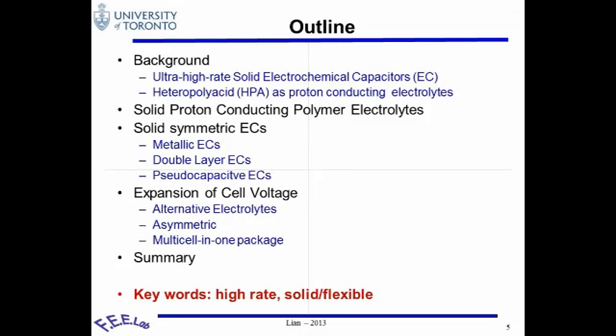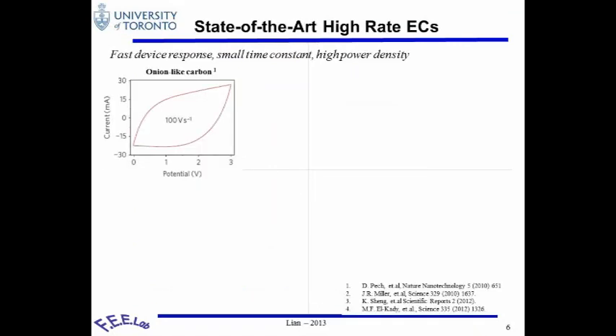So to start looking into high rate, most of the time the electrochemical capacitor has been developed by focusing on how to improve the energy density, meaning increase the capacitance. Look at how many farads per gram, which is important. However, as we see in the first slide that I showed, in the Ragone chart, the electrochemical capacitor also has a very important function, that it can deliver high power. This is something that has been neglected for a while, but recently, starting about 2010, there are more and more efforts in this field.